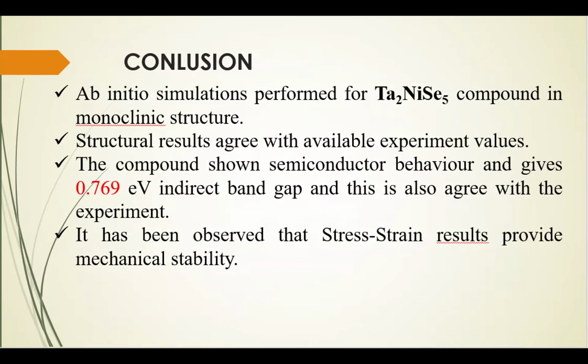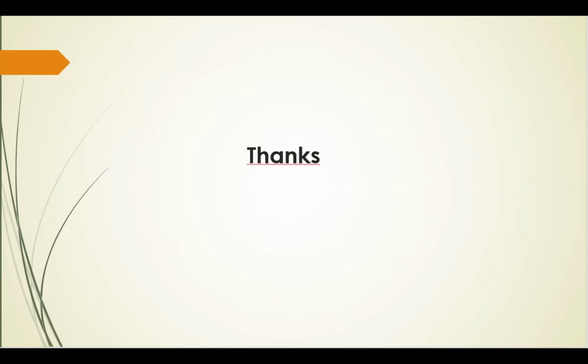Ab initio simulation was performed for the compound in the monoclinic structure. Structure results agree with the experimental values. The compound shows semiconductor behavior and gives a 0.769 electron volt indirect band gap, and this also agrees with the experiment. It has been observed that the stress-strain results provide mechanical stability. Thanks.